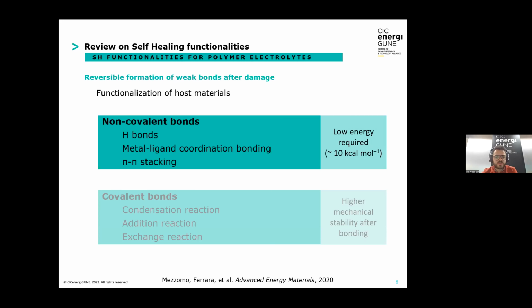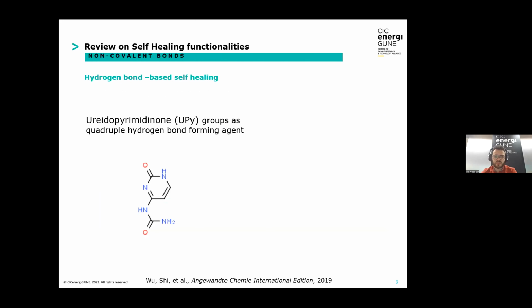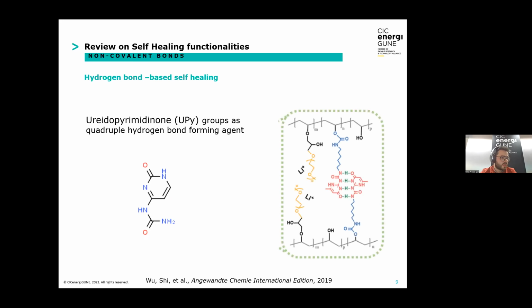Moving into the different examples for non-covalent bonds, the first example is hydrogen bonds, which, as you all probably know, are formed by a hydrogen atom and the lone pair of an electron-rich donor element such as nitrogen or fluorine. This is widely employed in the literature, particularly ureidopyrimidinone, since it forms quadruple hydrogen bonds, and it can be easily co-polymerized with other polymer matrices through these amino groups. In this example, the UPy is copolymerized with NCO and PVA to form a network where different UPy groups form four quadruple hydrogen bonds, as we saw in the previous presentation, that self-repair.